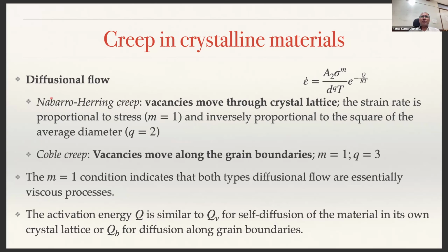In the literature it is called Nabarro-Herring creep, because Nabarro was a material scientist from South Africa. He contributed significantly to the understanding of plastic deformation of materials, and hence his name is given. This equation represents the Nabarro-Herring creep, where the vacancies move through the crystal lattice. The strain rate in this case is proportional to stress, m equal to 1, and inversely proportional to the square of the average diameter. That means in Nabarro-Herring creep, m is equal to 1, q is equal to 2.